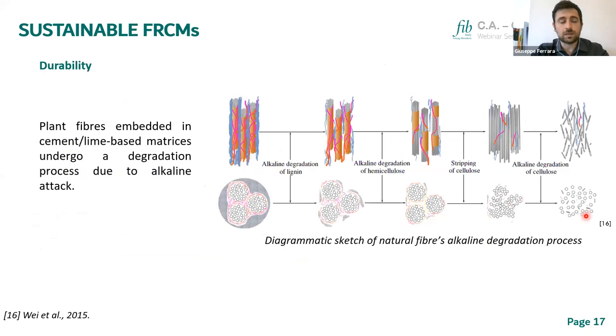of materials. Another crucial aspect, as I was saying before, is durability. Actually, the durability properties of plant fibers, as Jacopo was also saying before, are critical for all types of materials and FRCMs. But in the case of plant fibers, we have to know that once they are imbibed in cement or lime-based matrices, they undergo a severe degradation process due to alkaline attack. I won't go too much into detail on this aspect, but we have to know that chemically, plant fibers are made of lignin, hemicellulose, and cellulose. And the cellulose is the part that confers the mechanical resistance to the fibers.